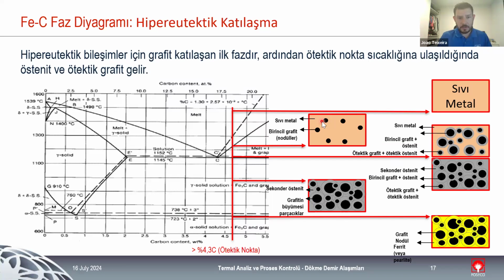When you have a lot of graphite being formed really early during solidification, we have what we see here in this small picture. We have big nodules and we have small nodules. So we have a really quick expansion of the graphite. This is important for some applications where we need this quick expansion of graphite. But at the same point, we have a lot of problems with this. The main one is that the graphite being less dense than the liquid metal, the graphite nodules, I said nodules because I'm thinking about nodular cast iron, but the graphite being less dense starts to go to the surface and it can block the gating system.